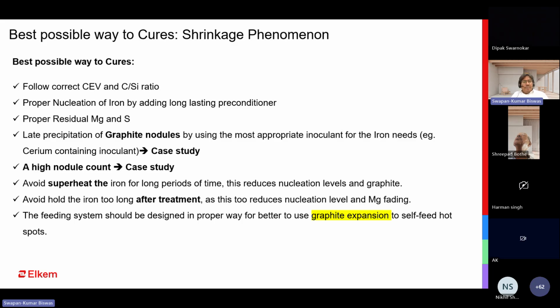When the initial graphite precipitation is on the higher side, there are always chances of more expansion. But at the later stage, there is no nucleation site to create the last stage graphite precipitation. Only a cerium containing inoculant gives primary plus secondary graphite precipitation. So you have to select this inoculant along with your ferrosilicon magnesium, which helps to control the microporosity. In a barium base, you will not get 100% benefit in controlling microporosity.